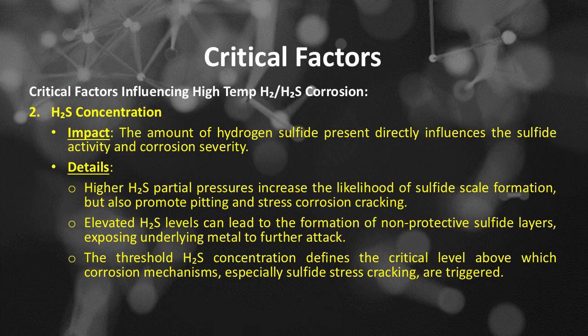Critical factors influencing high-temperature hydrogen or H2 and hydrogen sulfide or H₂S corrosion. Number 2 is H₂S concentration. The H₂S concentration impact. The amount of hydrogen sulfide present directly influences the sulfide activity and corrosion severity. For details, higher H₂S partial pressures increase the likelihood of sulfide scale formation, but also promote pitting and stress corrosion cracking. Elevated H₂S levels can lead to the formation of non-protective sulfide layers, exposing underlying metal to further attack. The threshold H₂S concentration defines the critical level above which corrosion mechanisms, especially sulfide stress cracking, are triggered.